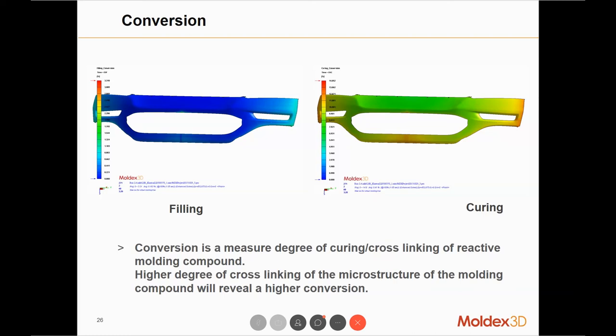For the curing stage, on the other hand, we would like to check whether the conversion rate is high enough. If at the end of curing, the conversion rate is still too low, that means the part is simply not hardened enough. Without enough cross-linking, the mechanical strength won't be high enough, and the part will not be ready for ejection. So with a low conversion, the users might need to increase their curing time. So this result helps users to determine a proper curing time, which can save a lot of our production cycle time, which equals our production cost.